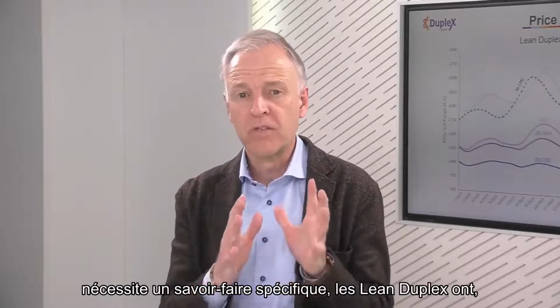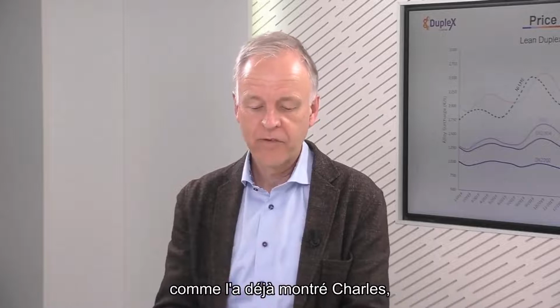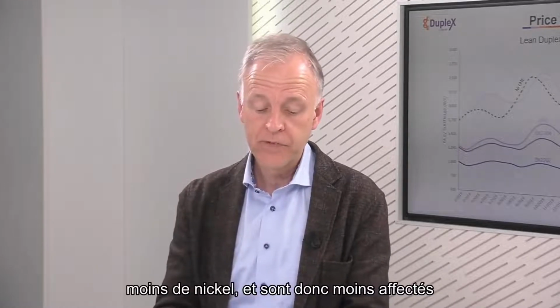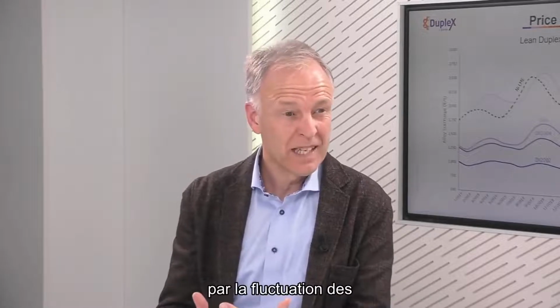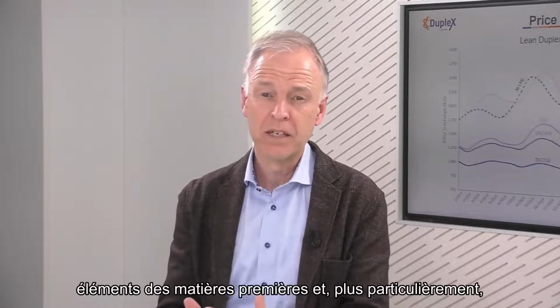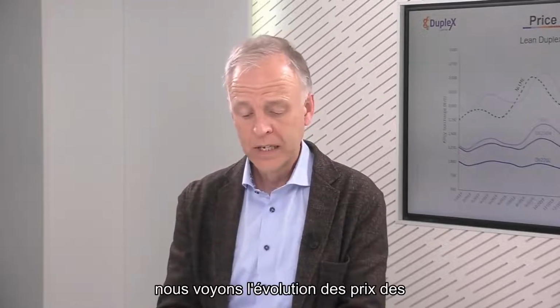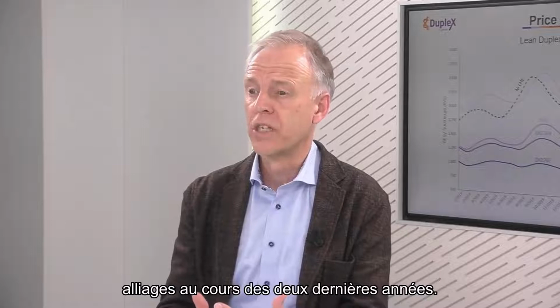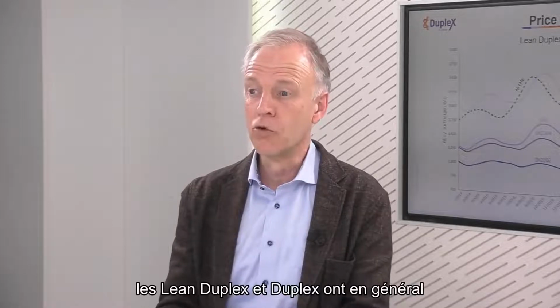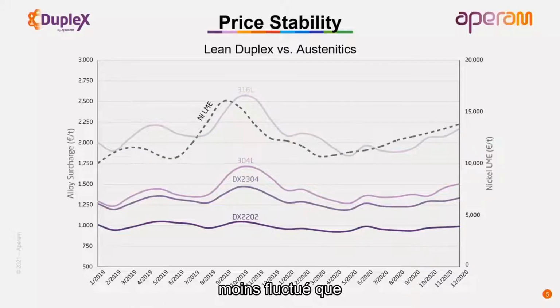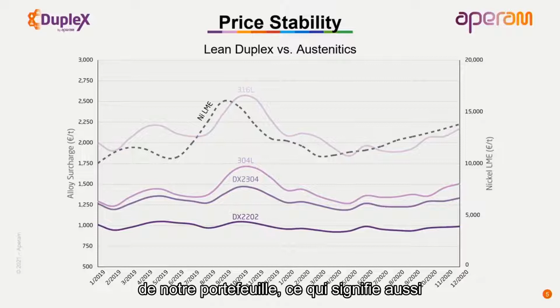Well, although the manufacturing process of these grades requires specific know-how, the lean duplexes have, as already shown by Charles, less nickel, and so they are less affected by the fluctuation of raw material elements, and specifically with nickel. We have here in the graph shown the evolution of the alloy surcharges over the last 2 years, and you see clearly that compared to classical 304, 316L, the lean duplex and duplex in general are fluctuating less than the standard grades in our portfolio, which means also that these lean duplexes offer a more stable pricing to our customers,